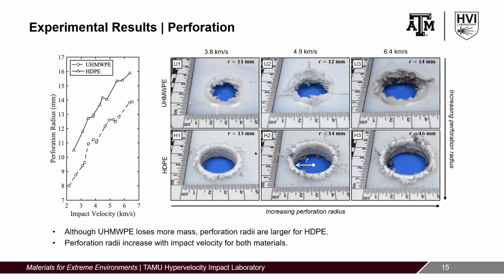Additionally, the hypervelocity impact-induced perforation region was analyzed for all specimens. The measured perforation radius is shown as a function of impact velocity for both ultra-high molecular weight polyethylene and high-density polyethylene. While ultra-high molecular weight polyethylene loses more mass at similar impact velocities, high-density polyethylene exhibits a larger perforation diameter for the impact velocity regime tested.